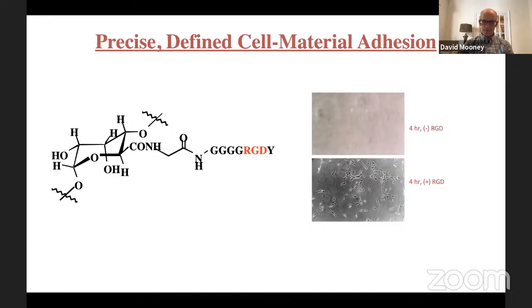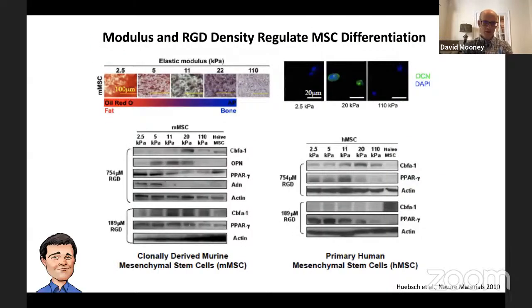Now, Nate Huebsch, shown here in the lower left, who's now running his own lab at Washington University, was the first to demonstrate that in 3D, one could indeed regulate the fate of stem cells simply by varying the mechanical properties of the gel. So here he took MSCs, he put them in gels that were either very soft, as indicated by an elastic modulus of 2 to 2.5, and these cells actually differentiated and became fat-forming cells or adipocytes.